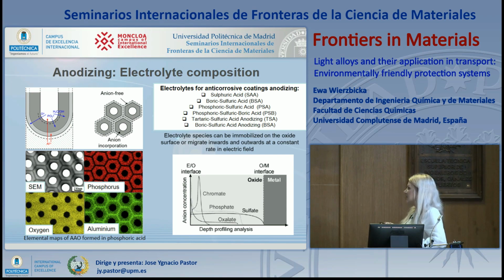Those are the electrolytes that are typically used for aluminium anodizing. They are acids. As I said before, the incorporation of electrolyte species in the case of conventional anodizing is not as big as in the case of PEO. The anions are introduced into the coating by simple migration in the electric field, so their distribution can be different through the depth of the oxide profile. Also, due to the mechanism of formation of this oxide, there are regions that are free from these electrolyte species.